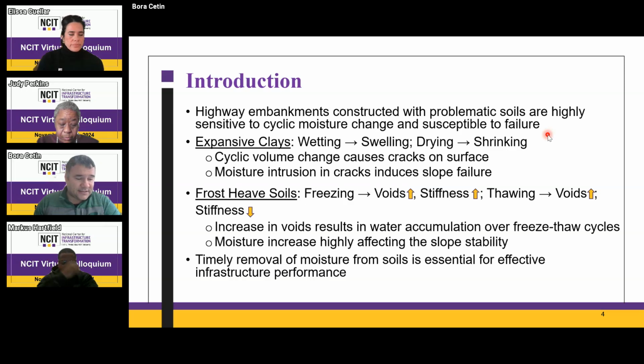Just like you can understand from the title, Michigan State is in the northern part of the country, and the other three consortium partners are in the southern part of the country. So the climate is completely different. In Michigan, we have extreme numbers of freezing and thawing cycles, and we have frost susceptible soils, which can be significantly impacted by these freezing and thawing actions. In the southern part, especially in Texas and certain parts of Arizona, we have a lot of expansive clays, and rainfall or flooding events are increasing significantly. Expansive clays subjected to wetting and drying cycles cause significant infrastructure problems as well. When wetting happens, it swells, and when the weather gets hot and dry very quickly, it shrinks, and that causes significant problems.